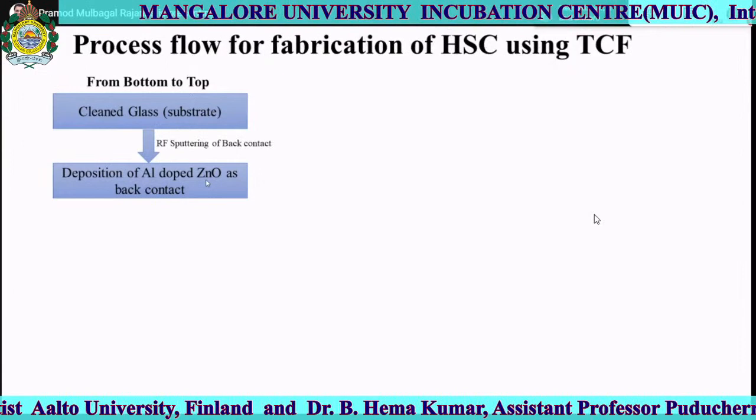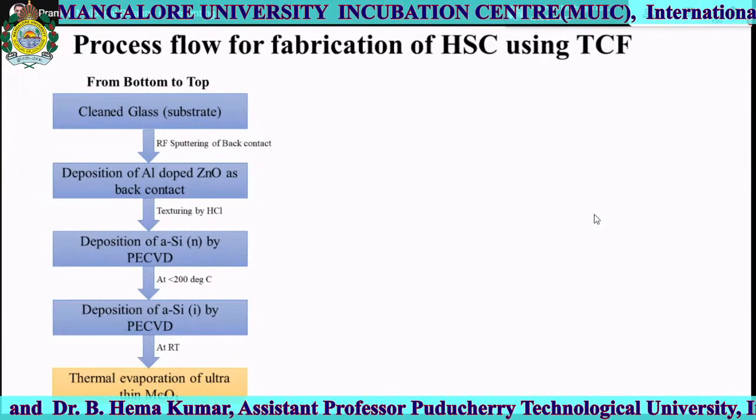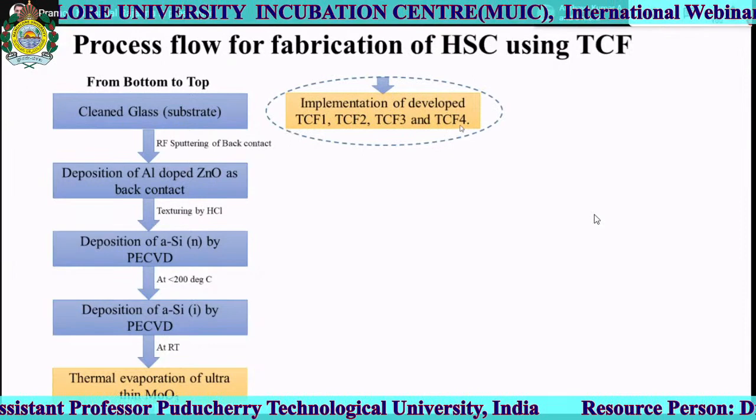So using these newly developed TCFs, we then went on to fabricate the device. So we have the clean glass, and then we repeat the process of sputtering aluminum zinc oxide as the back contact, and the N-type amorphous silicon, intrinsic amorphous silicon, and then we have the ultra-thin layer of molybdenum oxide on intrinsic amorphous silicon, thereby having a higher work function layer at the interface. And then we implement the developed TCF1 to TCF4, and this is how the stack looks.